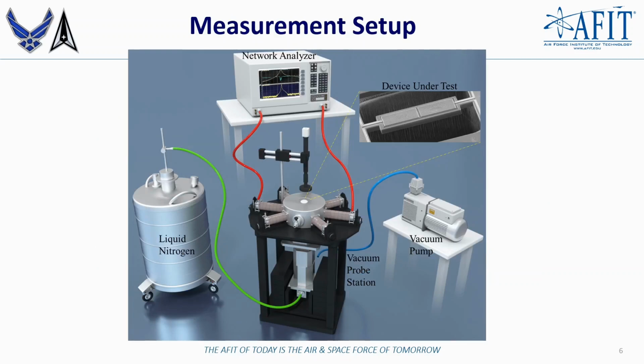So this slide shows the measurement setup we use to characterize the performance of our fabricated resonators. The device under test here was placed inside a Lakeshore vacuum probe station, where we conducted 2-port S parameter measurements over a broad range of temperature from -200 up to 200 degrees Celsius using liquid nitrogen for cooling.